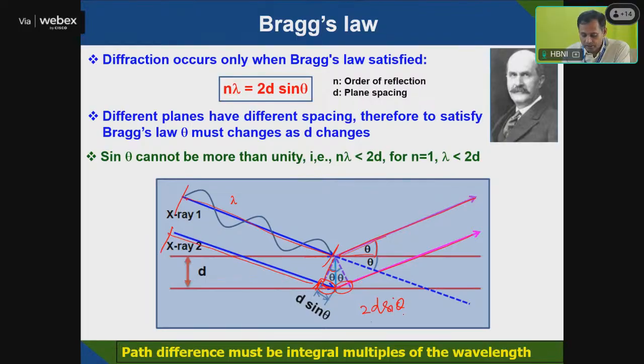The 2d sine theta should be equivalent to an integral multiple of your wavelength. n lambda equals 2d sine theta. n can be the order of reflection: the first order n equals 1, second order n equals 2, and so on. So whenever Bragg's law is satisfied, you will be able to see a diffraction peak. Since sine theta can't be more than unity, n lambda will always be less than 2d. So the wavelength should always be less than 2d.